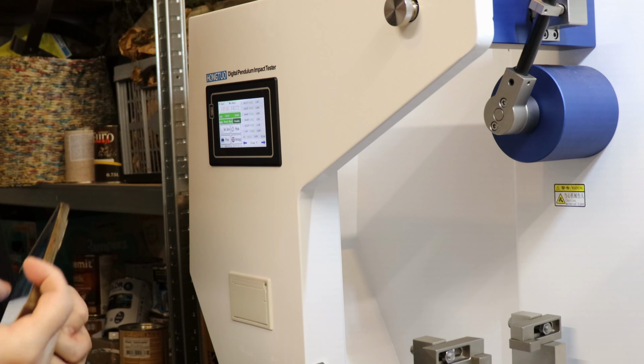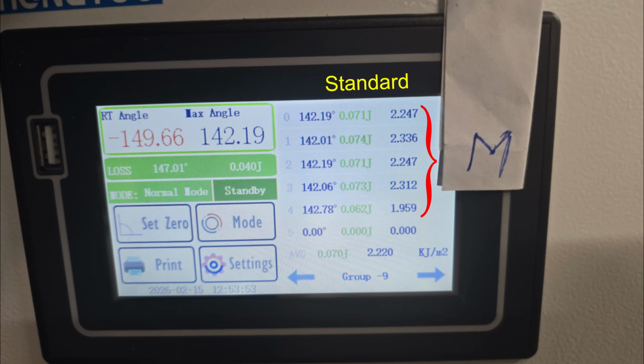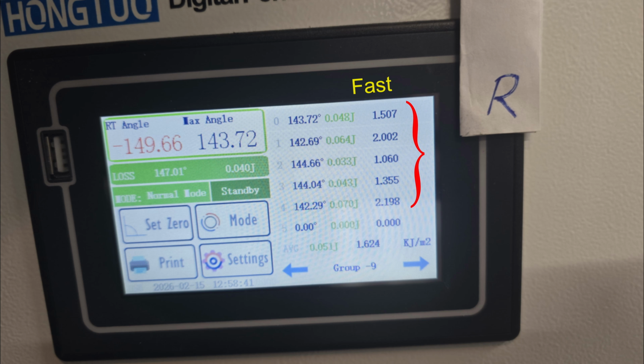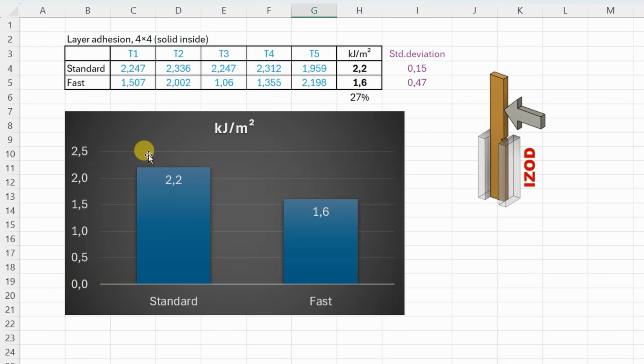Picture for the documentation, result for the standard speed, and for the fast printing. Again, standard speed stronger compared to the fast printing by approximately 27%. But one more interesting data, the standard deviation is much smaller with standard printing compared to the fast printing. This means a more constant quality we have with the slower printing.